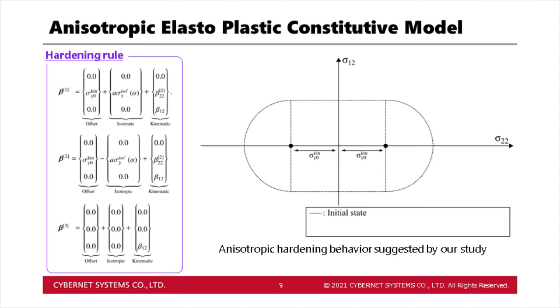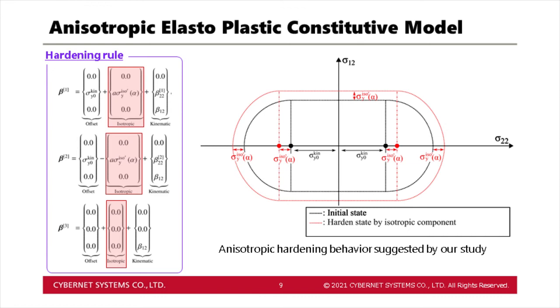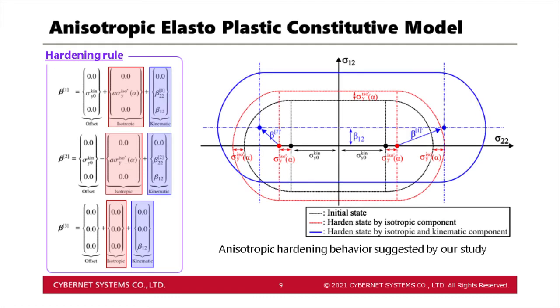In isotropic hardening, the yield surface maintains a similar relationship to the initial state, so it changes as shown in the red line of this figure. The important thing here is that in order to maintain the similarity relation, the center position of the arc must have moved. This is the second term of the hardening rule. Finally, there is a back stress that develops in conjunction with plastic strain. I will not explain in detail due to time constraints, but our model can express the distortion by developing back stress for tensile and compressive sides independently.